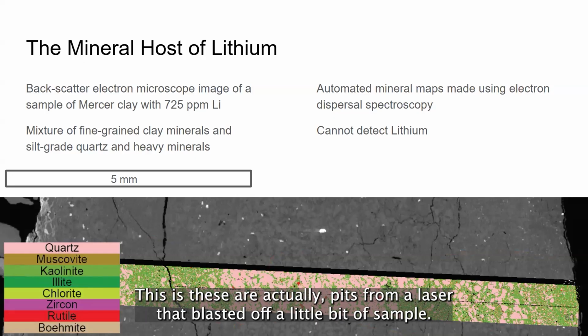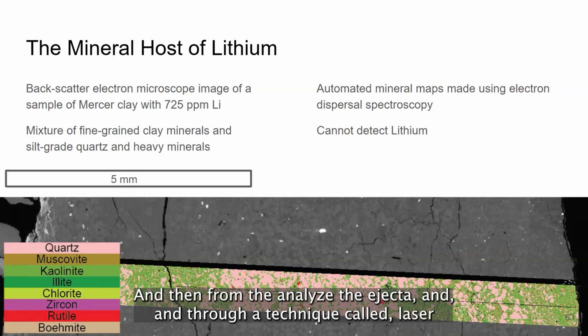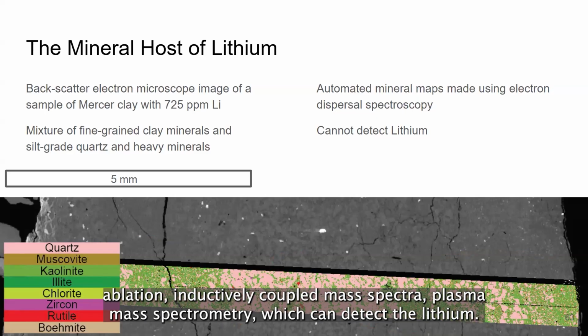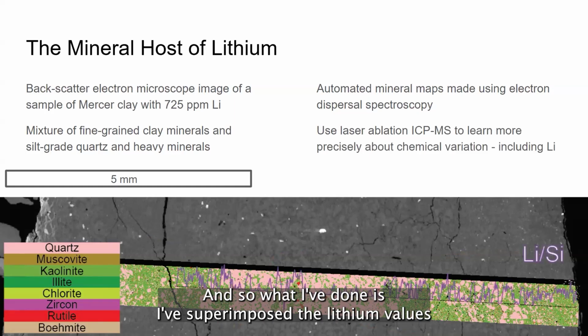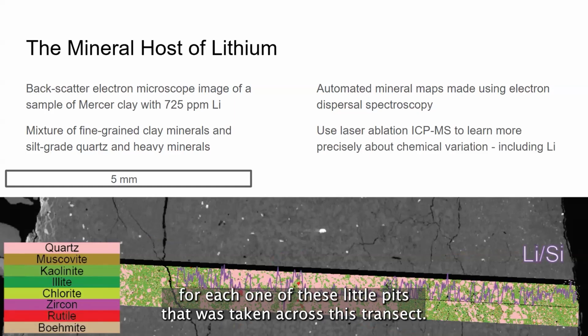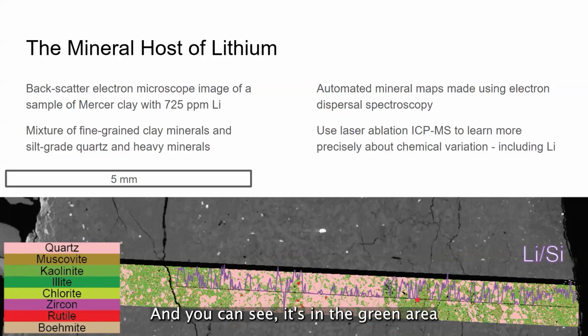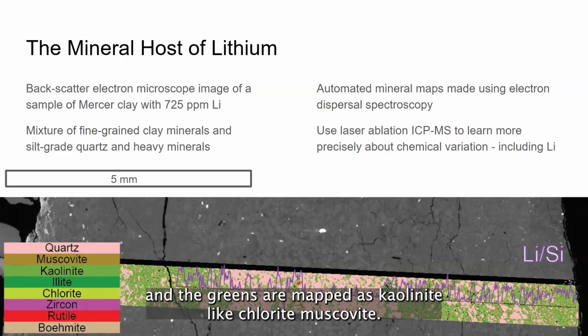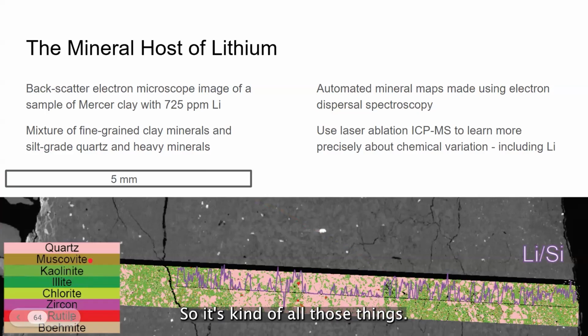These are actually pits from a laser that blasted off a little bit of sample, and then analyzed the ejecta through a technique called laser ablation inductively coupled plasma mass spectrometry, which can detect lithium. And so what I've done is I've superimposed the lithium values for each one of these little pits that was taken across this transect. And you can see it's in the green area. And the greens are mapped as kaolinite, illite, chlorite, muscovite. So it's kind of all those things.